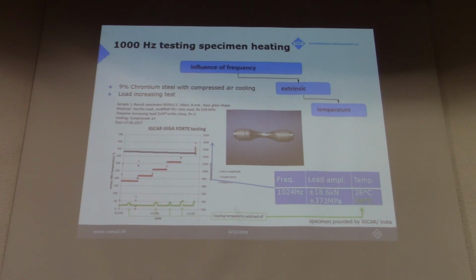We see here that with increasing load, the temperature is increasing. Here, this is the temperature, the green plot, and the temperature increases with increasing load. But we also can see that here with compressed air, in this case, we can control the temperature quite well, and continuous testing is possible.